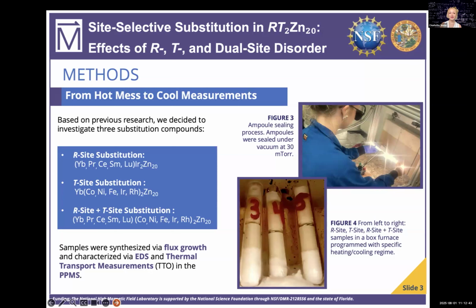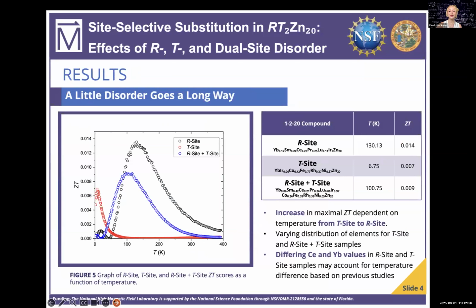After synthesis, we verified our compositions using energy dispersive spectroscopy, or EDS, and then we performed thermal transport measurements using the physical property measurement system. So our EDS results showed a somewhat even distribution of elements across samples, which possibly contributed to their difference in performance. But when we measured thermoelectric performance, we saw something really interesting.